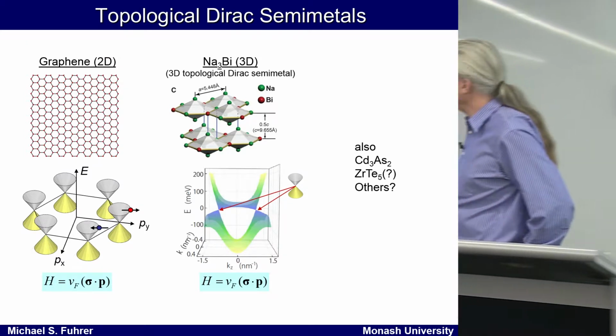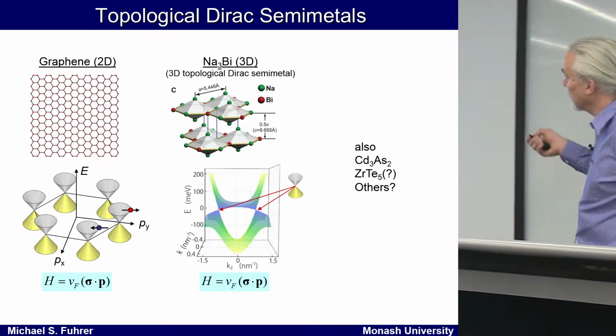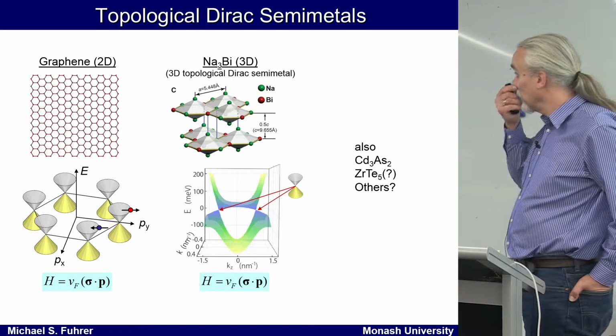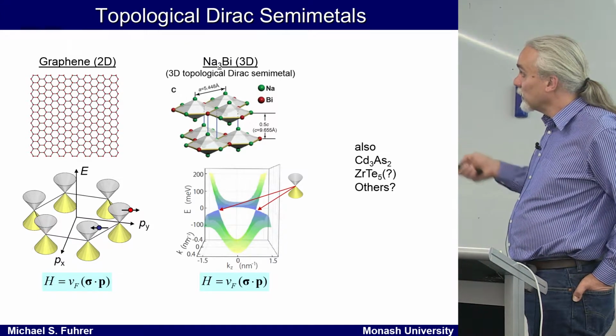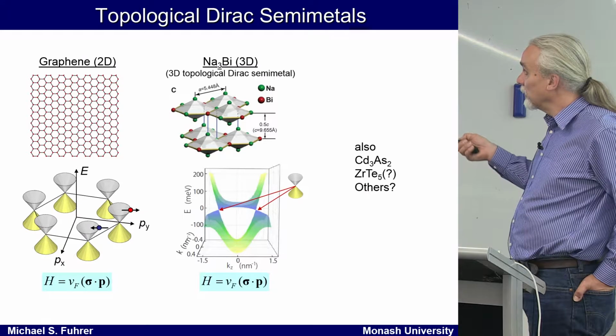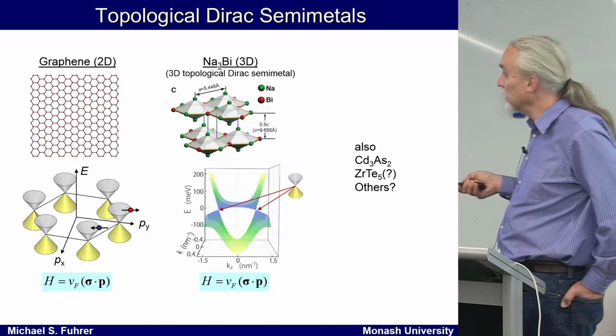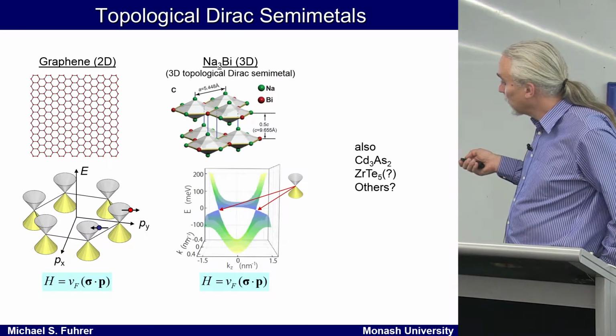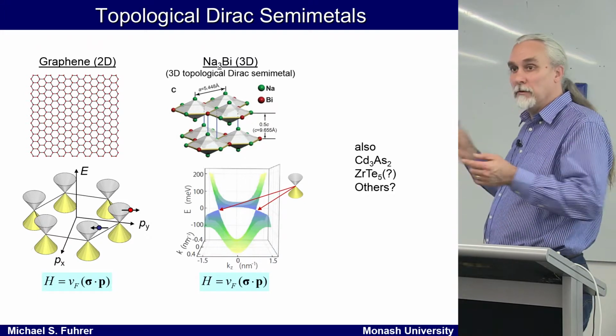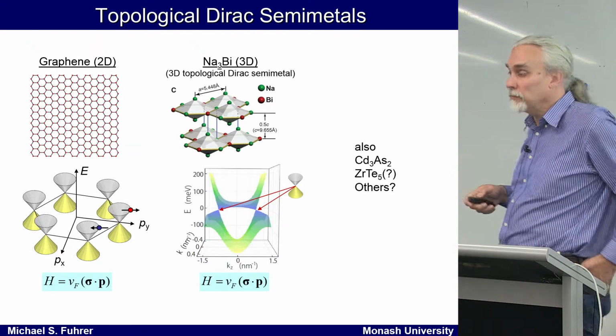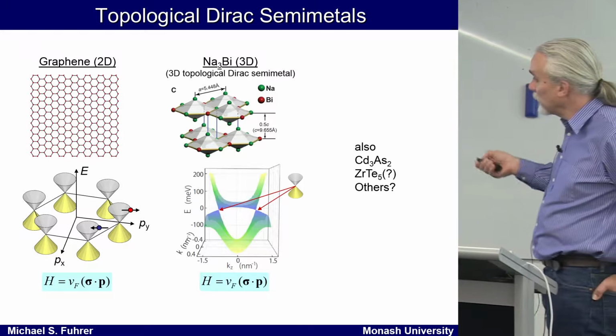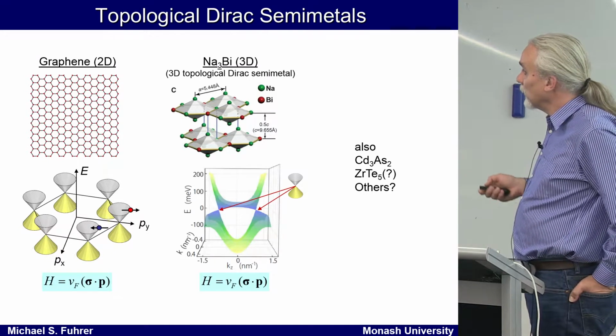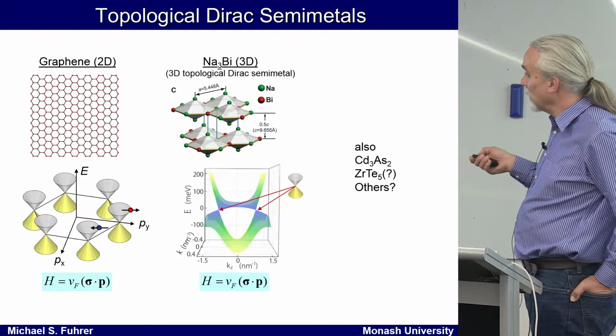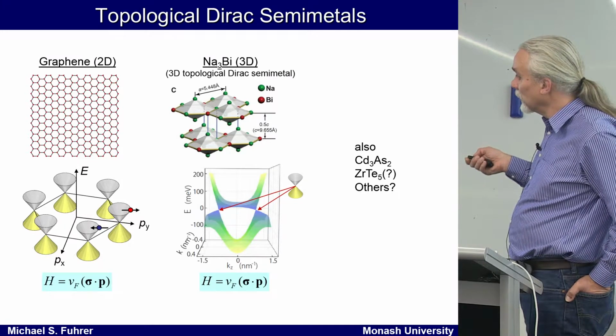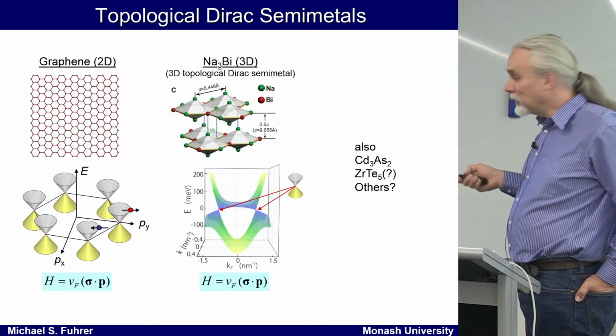So it turns out actually these things exist in 3 dimensions, and this is something that was realized only fairly recently, that there are 3-dimensional topological Dirac semimetals. Sodium-3 bismuth is one of these. It has this Dirac cone, but in all 3 momentum directions instead of just 2 as in graphene. And there are other examples of these 3D topological Dirac semimetals. Cadmium-3 arsenic-2 is clearly one. Zirconium telluride may be one, and there may be others.